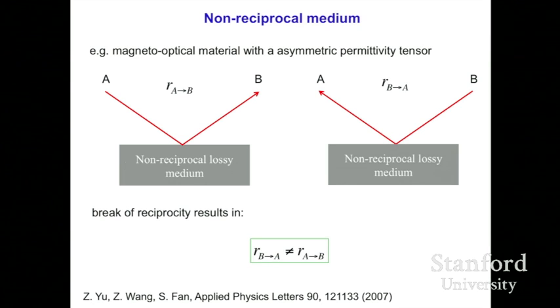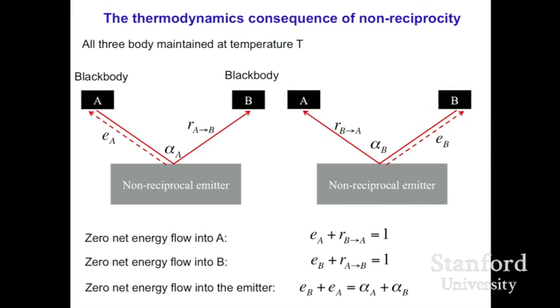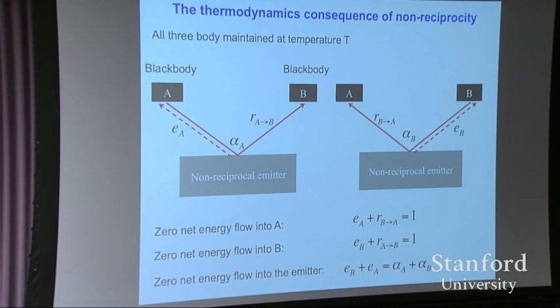On the other hand, if one were to break reciprocity by applying a magnetic field, for example, into some of these structures, then the reflectivity along these directions may actually be different. And in this case, one can show that the emissivity and the absorptivity between this emitter and the black body would be different as well. So breaking reciprocity will actually allow you the possibility of breaking detailed balance.